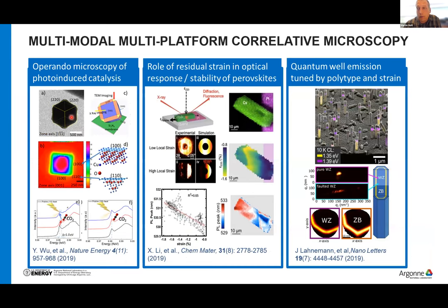All right, this can also be done in correlation with electron microscopy, and those are some of the things that we're trying to bridge. This is work with Yuzi Liu, where we're able to look at the same copper oxide nanoparticle, both in the electron microscope and also out at the beamline in the same scanning cell. So in the same gas flow cell, being able to activate this photocatalytic reaction of CO2 at the edge of these copper oxide particles, and through core level spectroscopy out at the beamline, we're able to look at the catalytic rates per facet identified in the electron microscope.